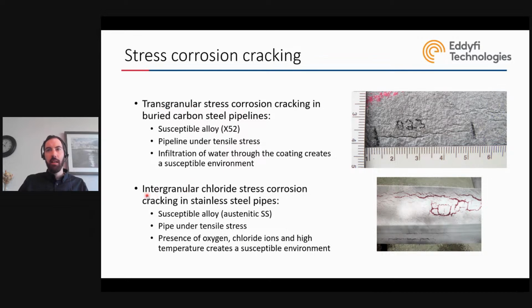In the case of SCC in stainless steel, this is different. This is what we call intergranular. The cracks will follow the edges of the grains, and we'll have a more or less linear orientation of the cracks themselves. This happens again in susceptible alloys, in this case typically austenitic stainless steel. Again, you need some high tensile stress in the steel to induce cracking. But finally, the main difference is the agent that initiates the cracks. In this case, we need oxygen and chloride ions. And when you also have high temperature, it creates an even more susceptible environment for cracking. So this is the difference between the two initiators of the cracks.